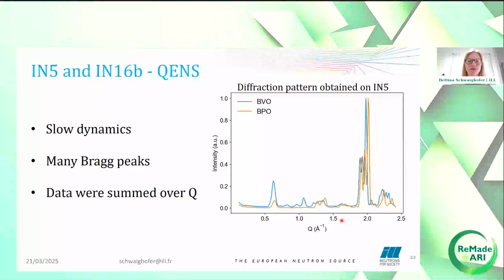To directly observe the diffusion of the oxide ions, we used IN5 and IN16B, so a time-of-flight spectrometer and a backscattering spectrometer. However, when measuring QENS on oxide ions, there are some limitations. The diffusion is generally quite slow, and especially complicated structures like this monoclinic structure I'm working on have many Bragg peaks in the range which is accessible through the spectrometers. Therefore, the signal is weak, and to allow us to extract the QENS broadening, we summed over Q values where the Bragg peaks were not present.